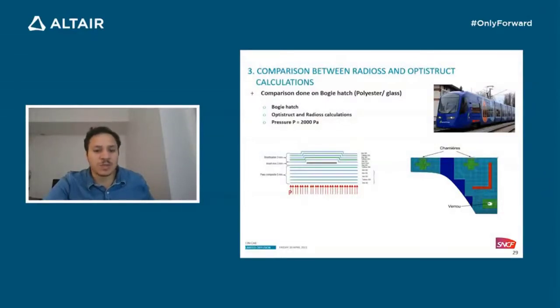Then we wanted to know if, with OptiStruct calculation, we can obtain conservative results compared to nonlinear calculation with Radioss. We also want calculations as quick as possible. For that, we use a bogie hatch used in a suburban train, as we can see here. Its localization is close to the bogie. We put in the calculation a 2000 Pascal pressure, the maximal pressure seen by this train.